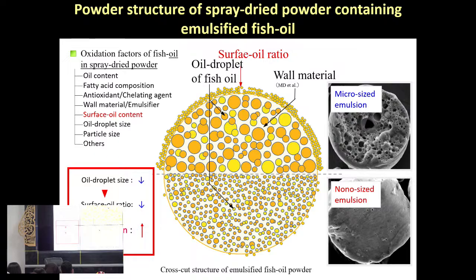So for example, this is the structure of spray dried powder containing emulsified fish oil, small oil droplet or large oil droplet. So we have to control the oil droplet size. Oil droplet size affects the surface oil ratio. So when we think about the stability of the oil in powder, we have to check the surface oil ratio. A small surface oil ratio is better to get stable oil.